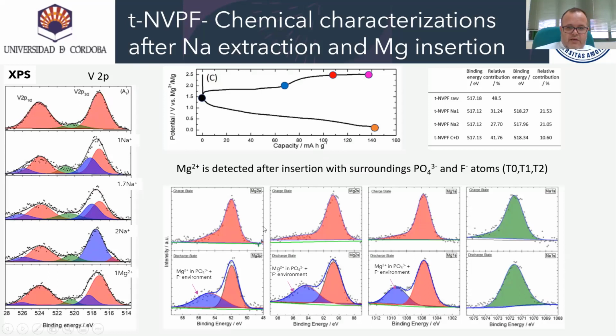Bottom right, here we have recorded the magnesium 2p, magnesium 2s, and magnesium 1s core levels. And they detected that after insertion, we observe an additional signal, which is in blue, due to the existence of magnesium ion with PO4 3- and fluorine surrounding atoms.